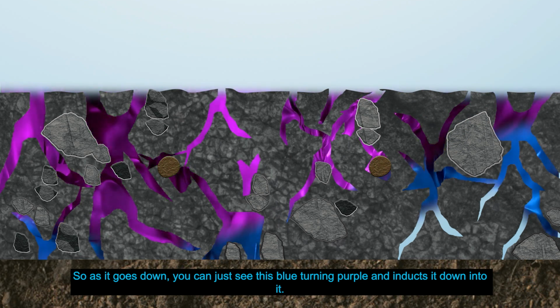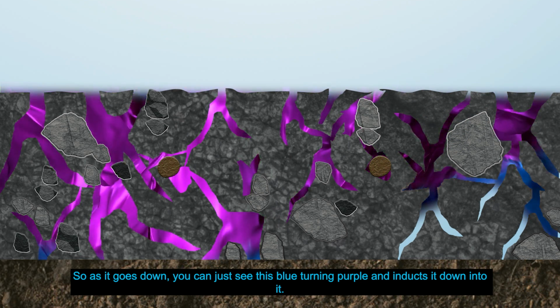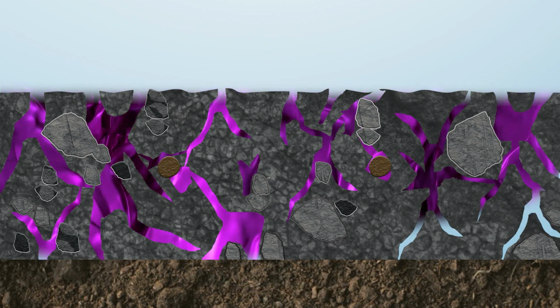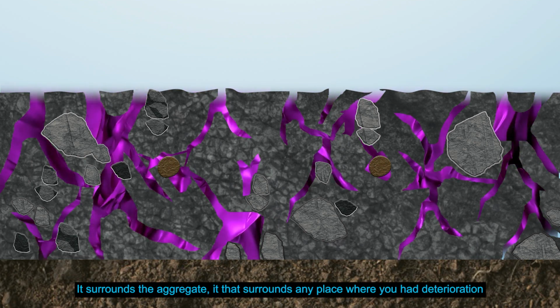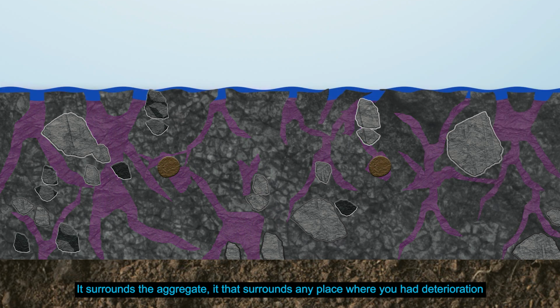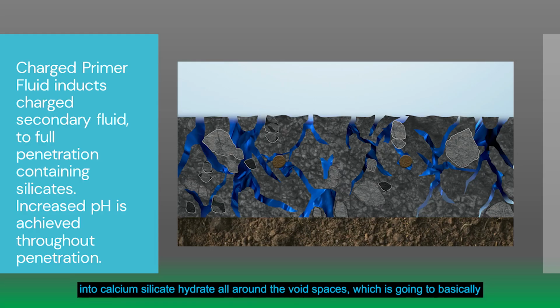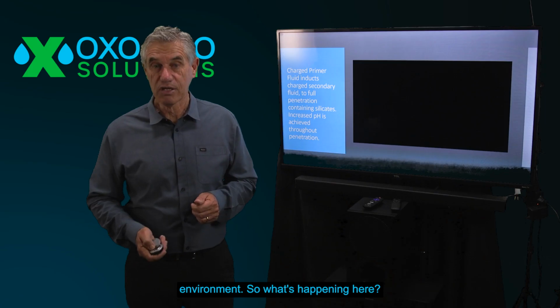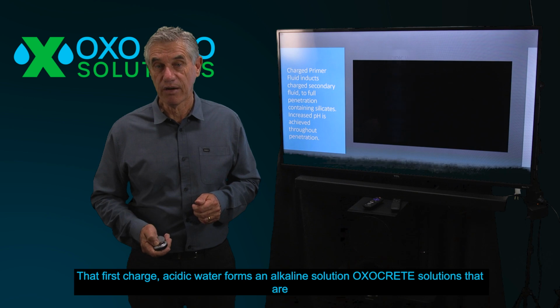So as it goes down, you can just see this blue turning purple, and it inducts it down into it. And it surrounds the steel, it surrounds the aggregate, it surrounds any place where you had deterioration before, and fills them with a silicate, in essence turning the calcium hydroxide into calcium silicate hydrate all around the void spaces, which is going to basically strengthen the whole matrix, harden it, and create a completely different cement environment.